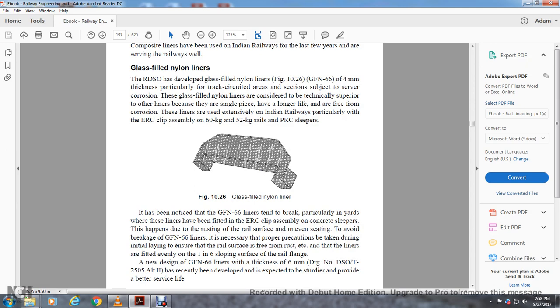Figure 26 of the glass-filled nylon liner. The failure of the GFN 66 liners was noticed particularly in the yards where the lines have to be provided with the ERC clip to assemble the concrete sleepers. This has been due to the rusting of the rail surface and even the seating of it, to avoid the breakage of the GFN 66 liner. The necessary proper precautions can be taken during the initial laying to ensure the rail surface is free of rust, etc. The liners are fitted evenly in 1 in 6 sloping surface of the rail flange.